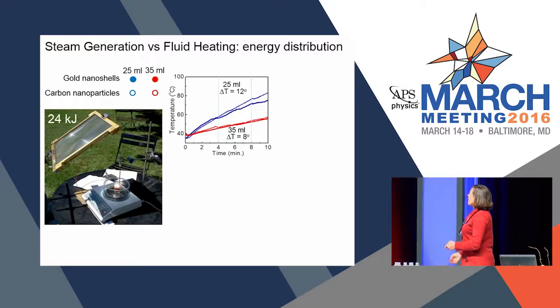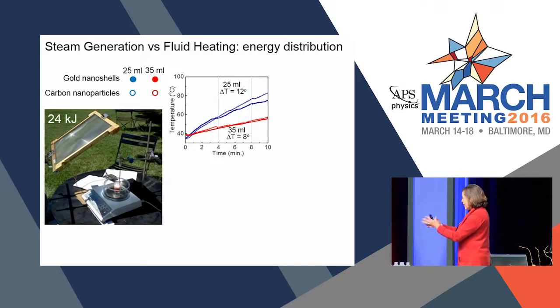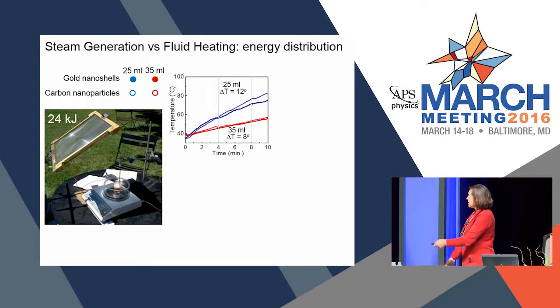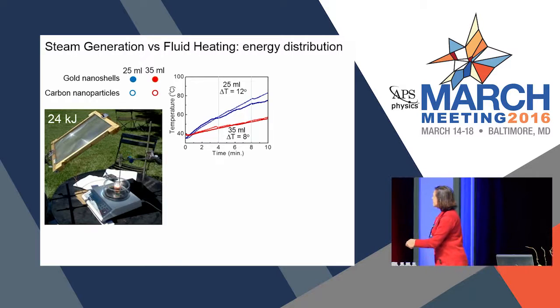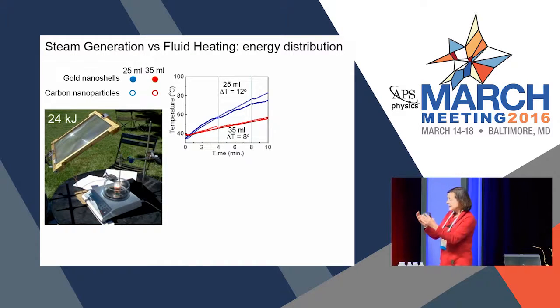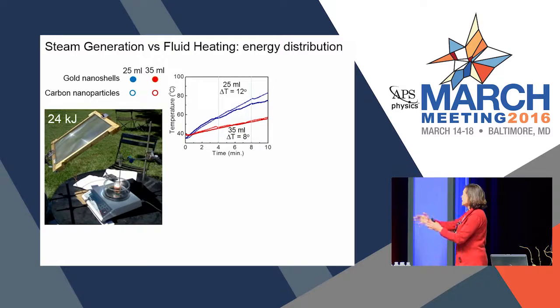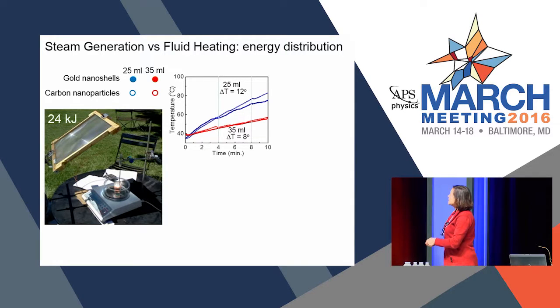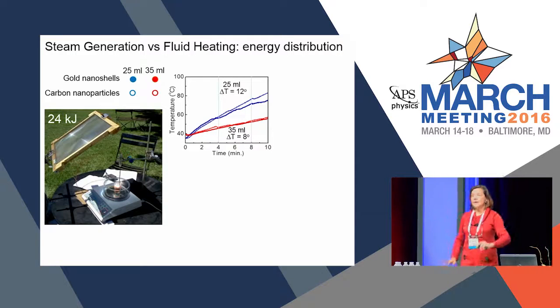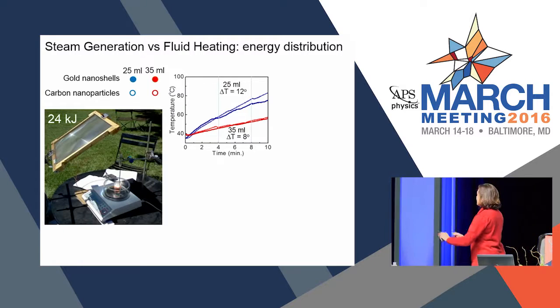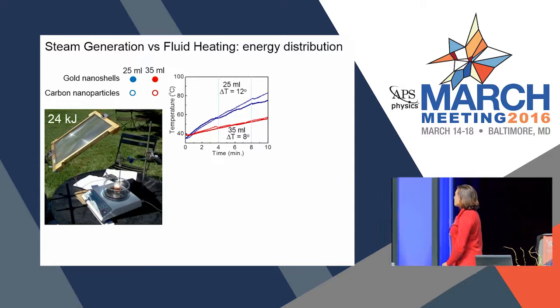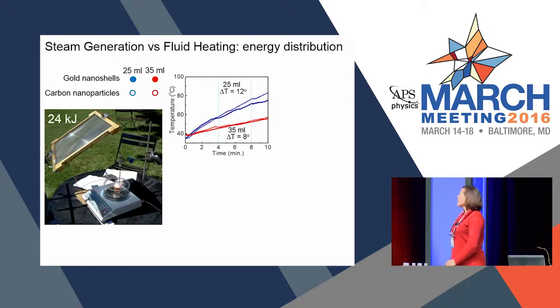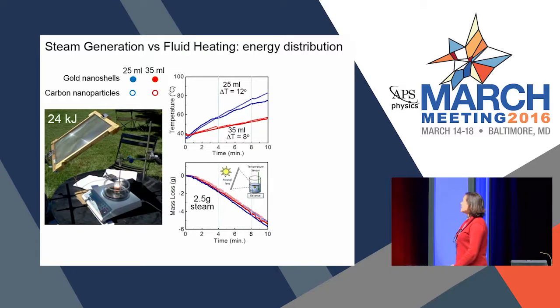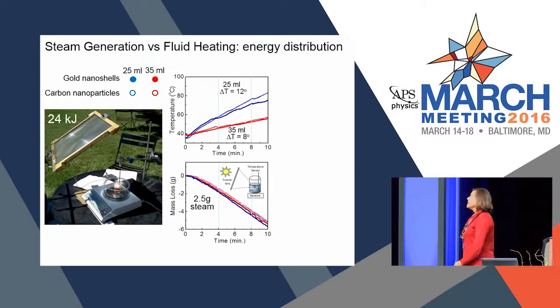And so if we take a mass of water, and then if we follow the temperature increase, we know exactly, this is basically the heat capacity, the mass, and then delta T. So if we have a larger mass, we have a smaller temperature increase, a smaller mass, larger temperature increase. That's all exactly what any junior high school or high school physics student would expect. If we look at the mass loss, the steam generation rate, it's identical.